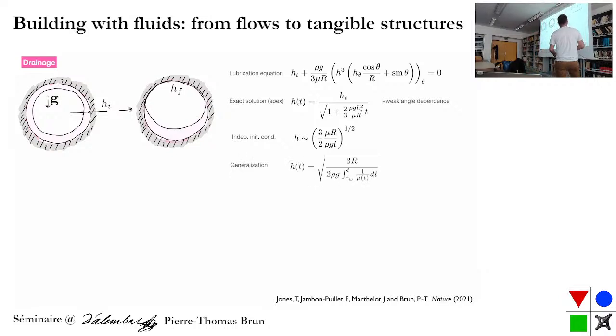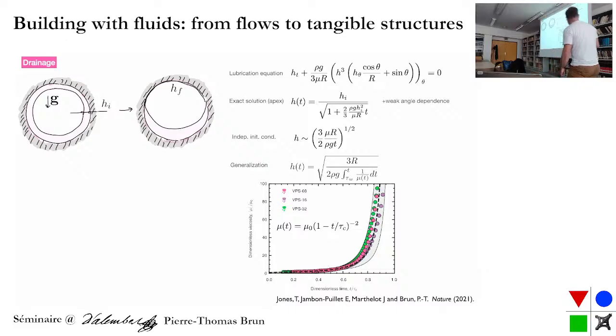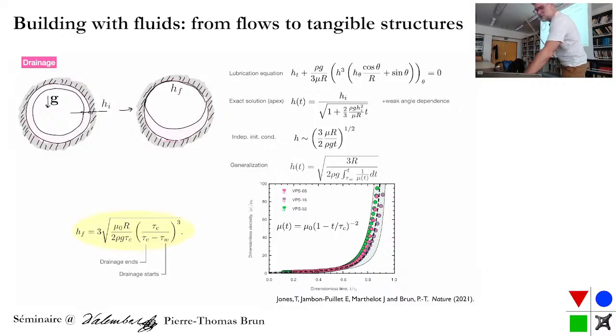If you do the same thing for an arbitrary viscosity, you have the integral of the viscosity. And I said a couple times already, but I'll show it now, that the viscosity is like a doomsday equation. And the doomsday equation, as we know, is almost constant and eventually goes to infinity. So if you do that, you can find the final thickness. So this final thickness is h sub f and depends on a number of things: the initial viscosity, the geometry, gravity, density, and mostly this curing time. Right? So when is it that this thing ceases to be a liquid and becomes an elastic?